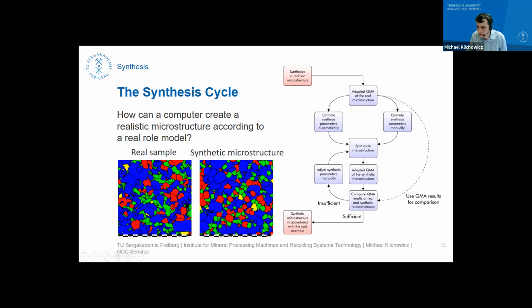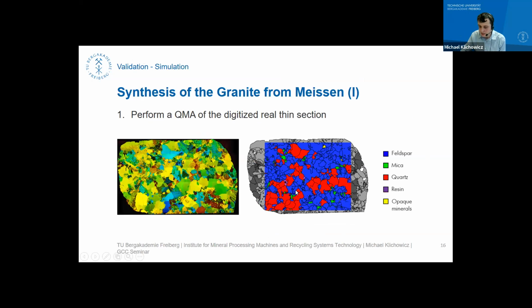sample, we do the analysis with the QMA, and we get the numbers for the grain size, for how many grains, how many faces we have, and so on. And then we can estimate the parameters for the synthetic microstructure. Then we create a synthetic microstructure and measure the synthetic microstructure again. And then we compare the results for both microstructures. And if there's no fit, if it is insufficient, we have to adjust the synthesis parameters. And we do this as long as the synthetic microstructure is not what we expected. But if we do it good enough, then we have at some certain point a microstructure that fits our needs. And I will show you this with a little example.